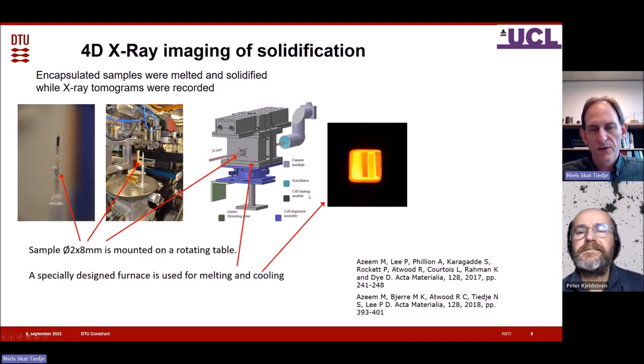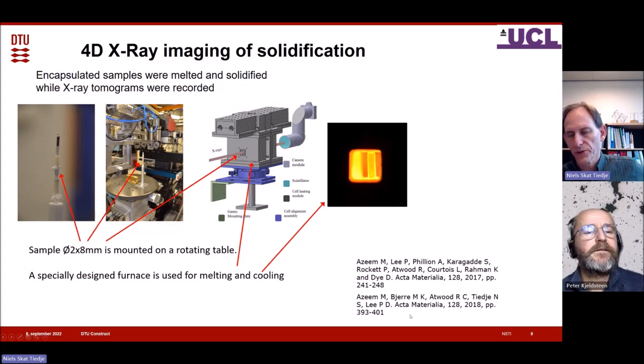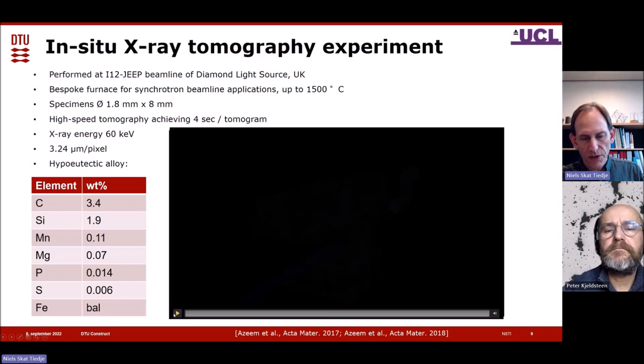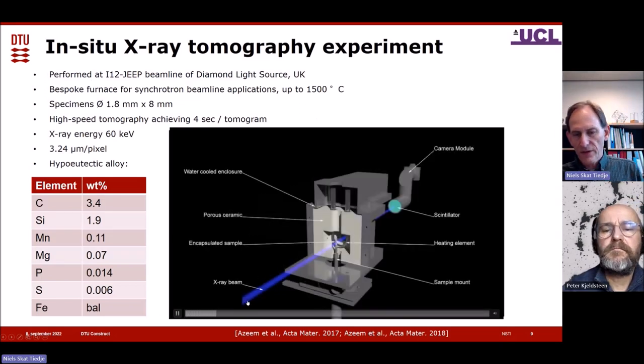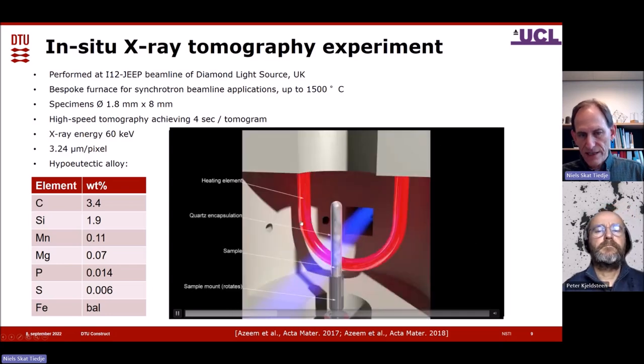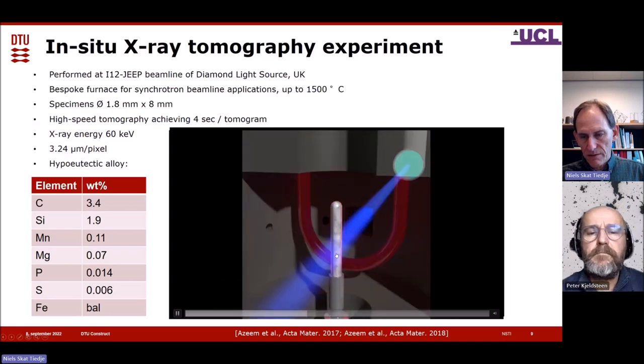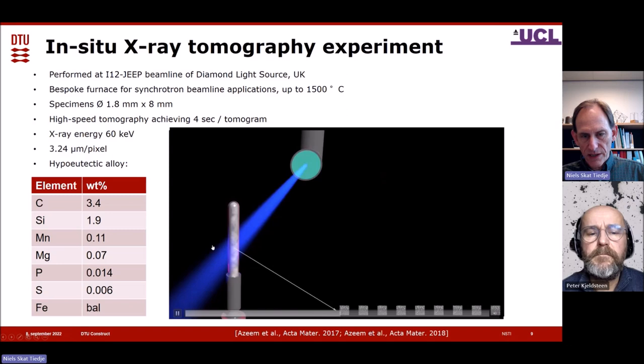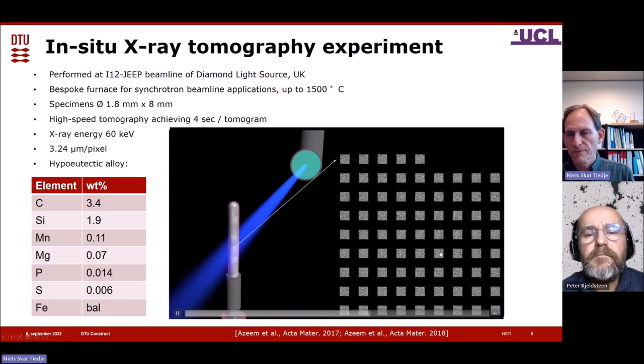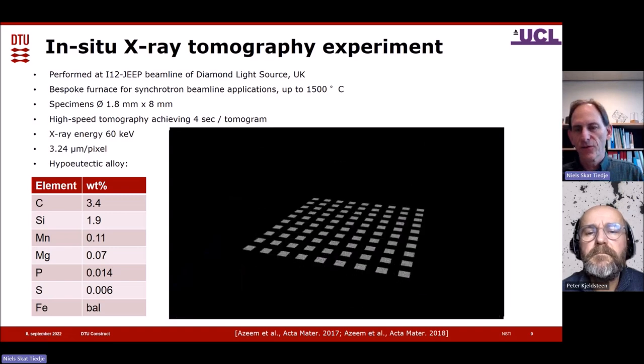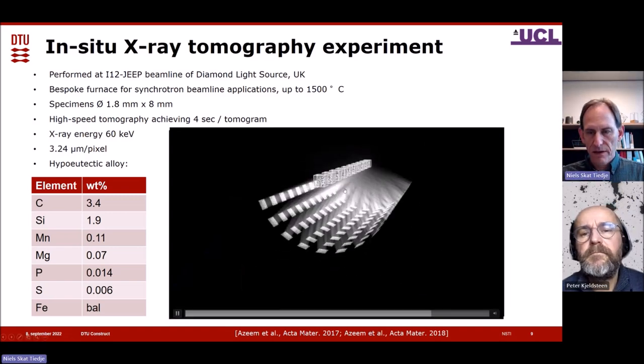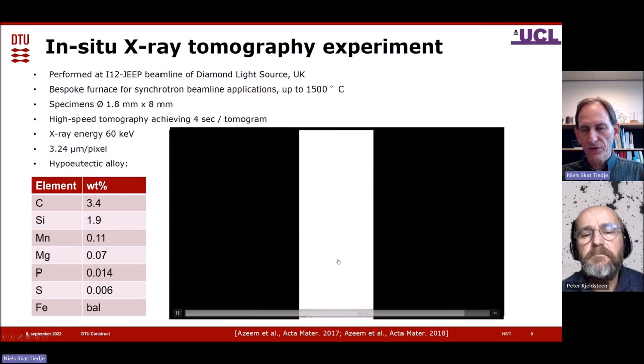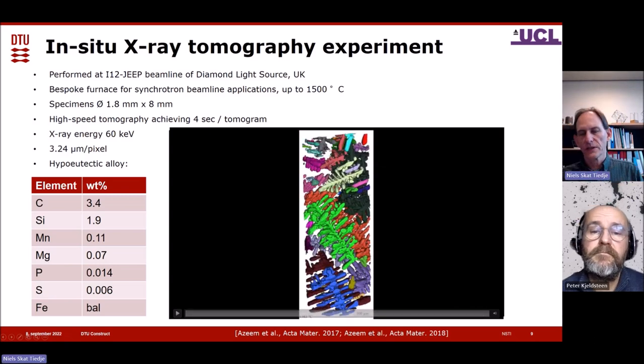Azeem and Peter Lee, people that actually developed the furnace bit of it and had access to the synchrotron. And then we had a group here at DTU that did the work together with those guys. And they made a nice video of how it works in practice. I can show that here. From the left, the X-ray beam. Here is our sample and a section through the furnace. The red is the heating element. And then the sample rotates. As you can see here, the sample rotates. X-rays go through and we acquire a lot of images. Those images can be stacked and form 3D images. And then you have 3D volumes that you can play as a video, as it's shown here.